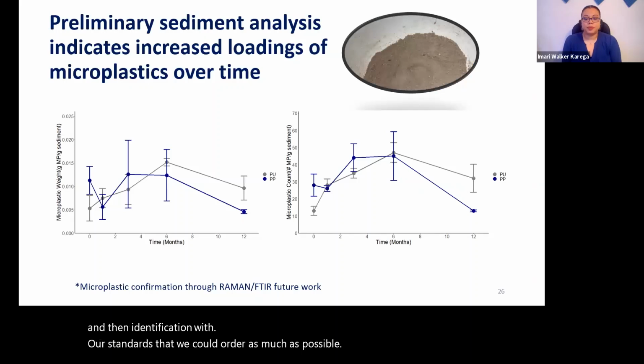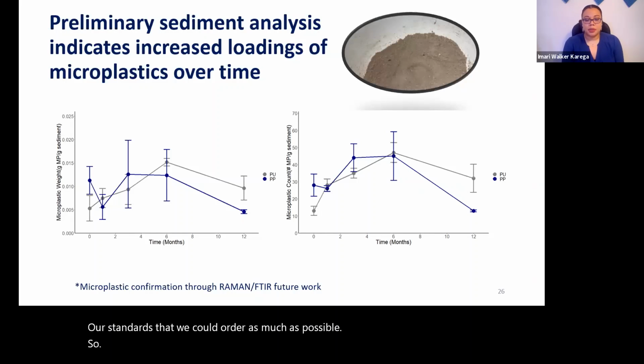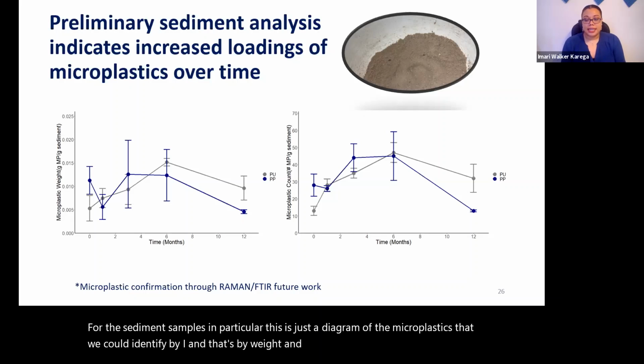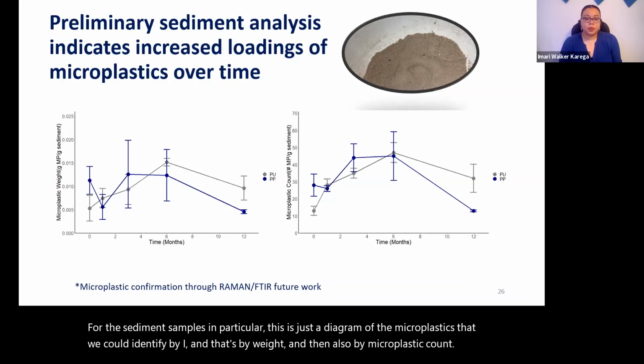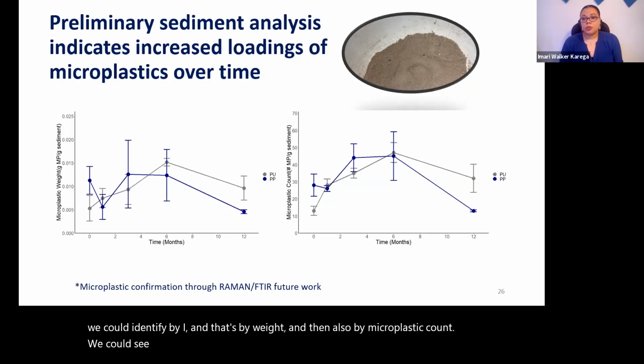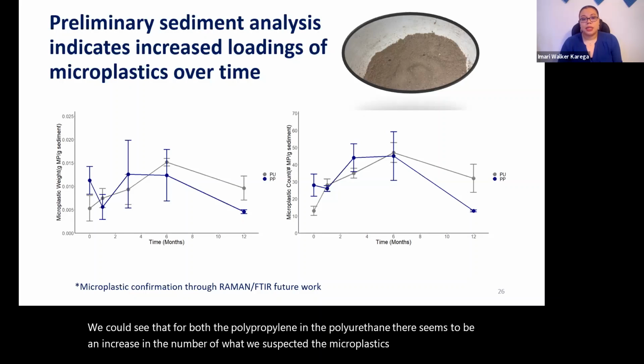For the sediment samples in particular, this is just a diagram of the microplastics that we could identify by eye, by weight, and also by microplastic count. We could see that for both the polypropylene and the polyurethane, there seemed to be an increase in the number of what we suspect to be microplastics over time, especially the first 6 months.